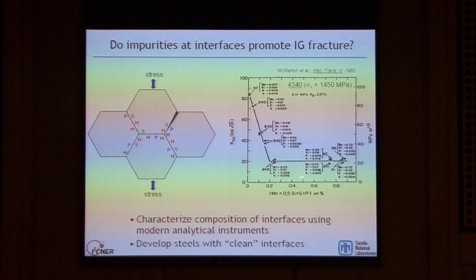What Professor McMahon did with this plot is look at steels with different compositions of phosphorus, sulfur, manganese, and silicon. Each data point represents a steel with a different composition, varying those four elements. In this plot he has some weighted average of these alloying elements, and on the y-axis is a measure of the hydrogen-assisted fracture resistance. You can see that at some point this parameter starts to increase quite dramatically.